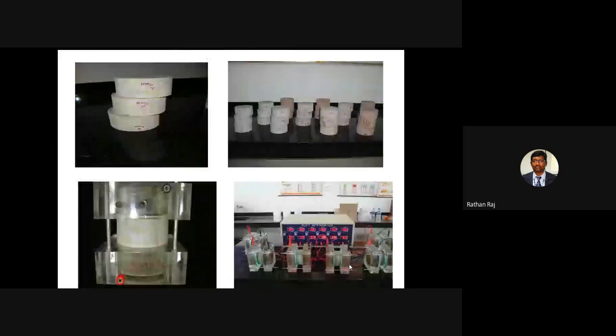These pictures show that initially the concrete cylinder was cast. The diameter is 100 mm and the height of the concrete is 200 mm. That concrete is cut with a diamond cutter into three parts: this is the top portion, this is the middle portion, and this is the bottom portion of the concrete, each disc of 50 mm thickness. Each of the top, middle, and bottom is separately fixed in the diffusion cell. So this is the diffusion cell.